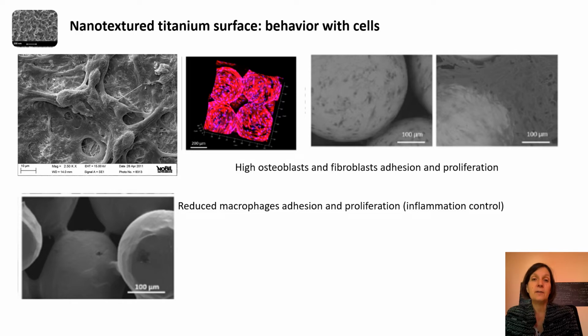And concerning the response by different cells, we can see here a high adhesion, proliferation and differentiation of the osteoblasts. And here we can see the treatment applied to a coating made of spheres of titanium, and you can see a high adhesion of fibroblasts that is quite higher than on the untreated surface. So the surface is suitable both for bone contact and soft tissue contact. And this is very interesting. There is a very low amount of macrophage adhesion and proliferation on the surface. So the surface is also able to induce a control of the inflammation response.